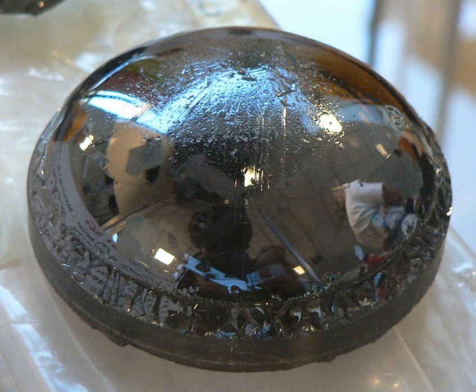The material formed in the Acheson furnace varies in purity, according to its distance from the graphite resistor heat source. Colorless, pale yellow and green crystals have the highest purity and are found closest to the resistor. The color changes to blue and black at greater distance from the resistor, and these darker crystals are less pure. Nitrogen and aluminium are common impurities, and they affect the electrical conductivity of SiC.